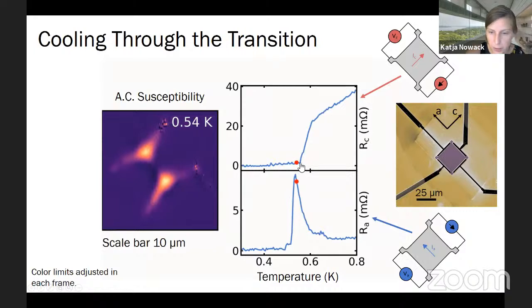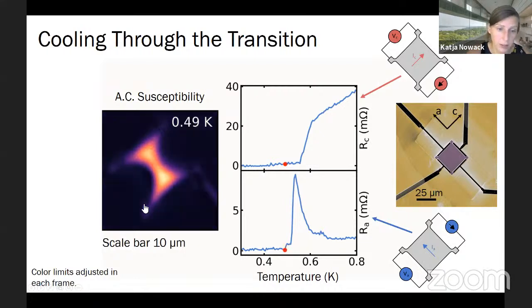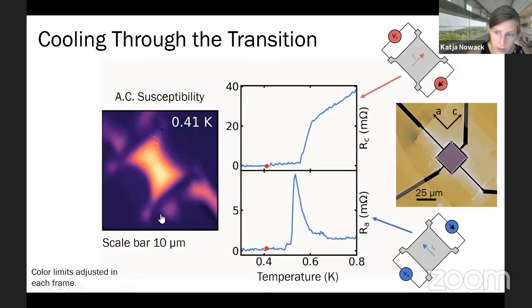Let's stop here. At this temperature, where in this transport configuration we measure zero resistance, we actually have extended superconducting regions connecting this contact and this contact and this contact and this contact. But there's no superconducting connection between this side of the sample yet and this side of the sample. And if we keep going, at this temperature all four contacts of the sample are connected by an extended superconducting region. If we go even lower in temperature, that superconducting region fills out and becomes bigger and bigger, and then other parts of the device start to superconduct.